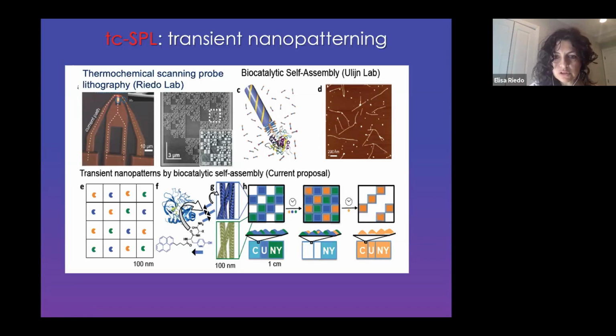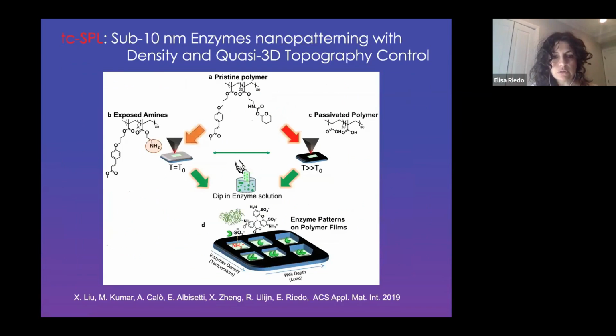Our part, so this was a collaboration with Professor Ulijn at CUNY, and our part, of course, is can we create patterns with single enzyme on the surface. So this work was performed in my lab with my student Shang Liu, and we call him Shun, with this type of scheme. So we start again with the pristine polymer that I showed you before. So this is a methacrylate copolymer, which exposes amine groups, okay?